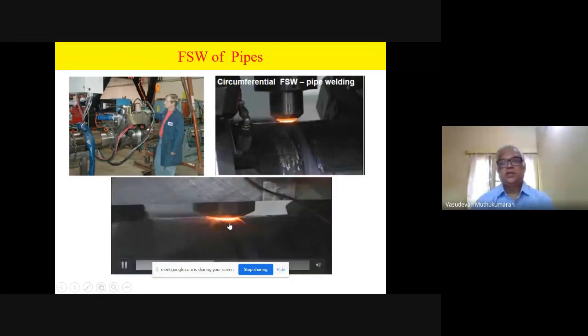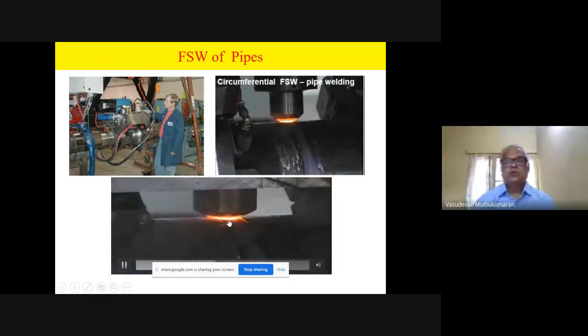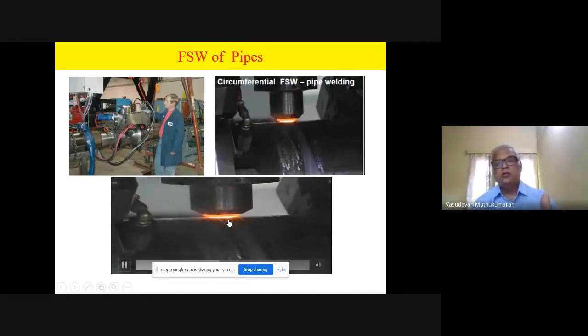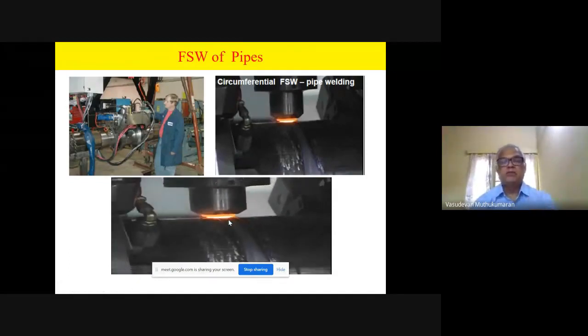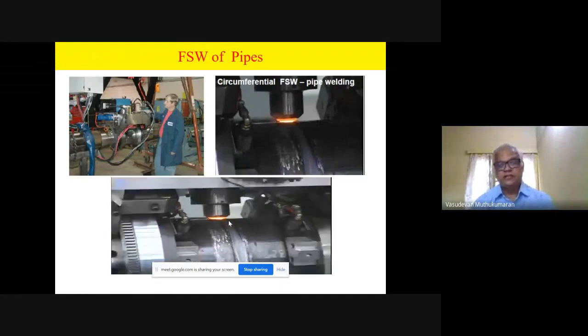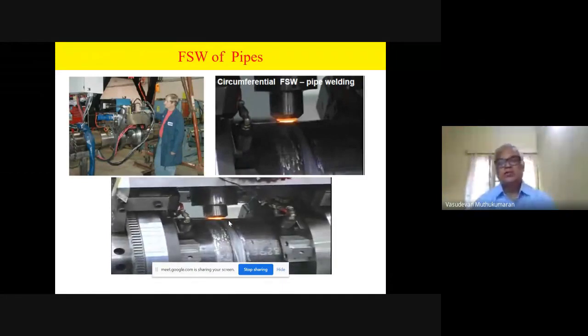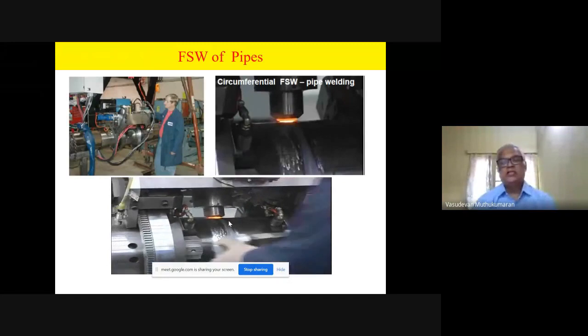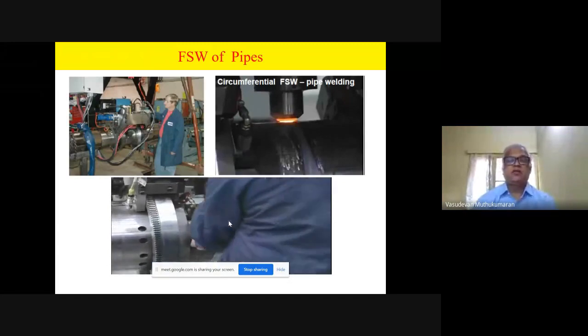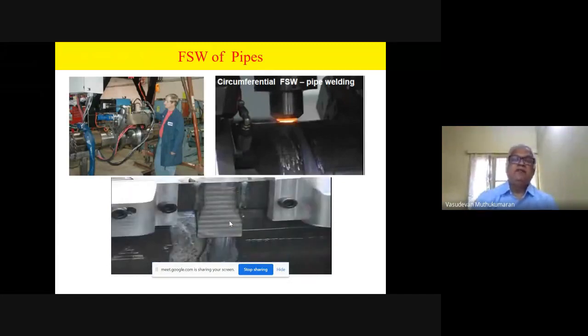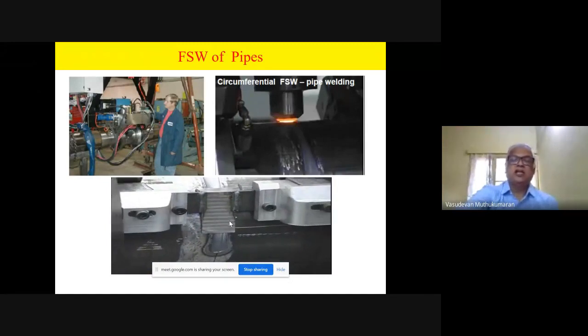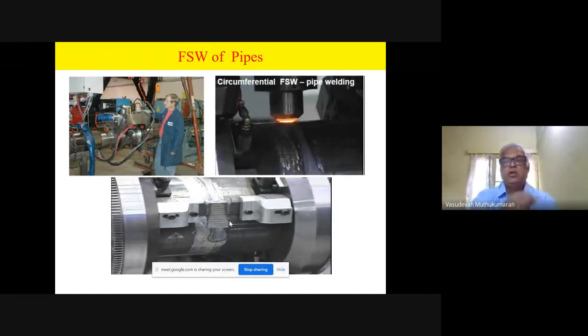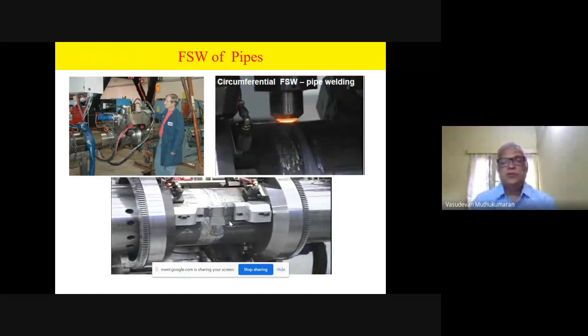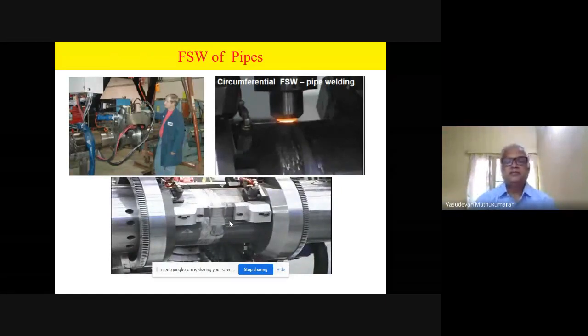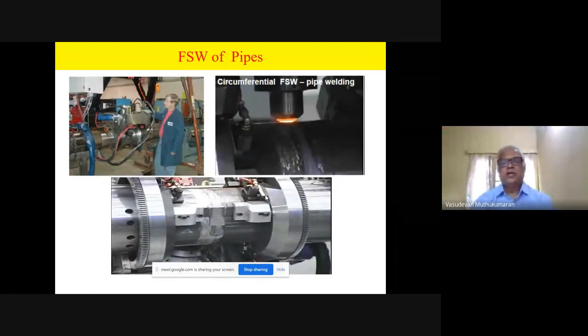See here, the generator. To avoid the hole at the end, they are doing something. You can see that they use an extra piece to stop the process so that the hole at the end is avoided. You can see here it is fixing the extra piece at the end. So welding will be completed at the extra piece, not in the pipe. And so the hole at the end is avoided. And he has fixed the extra piece.